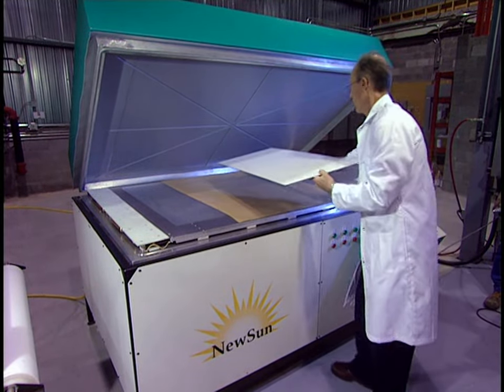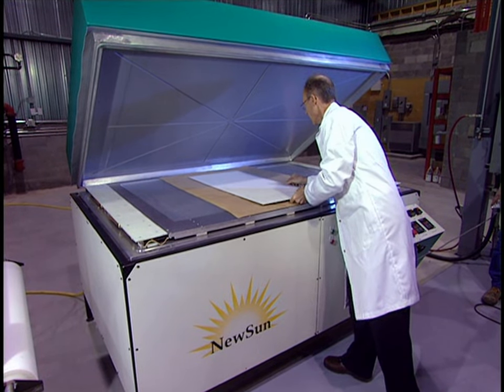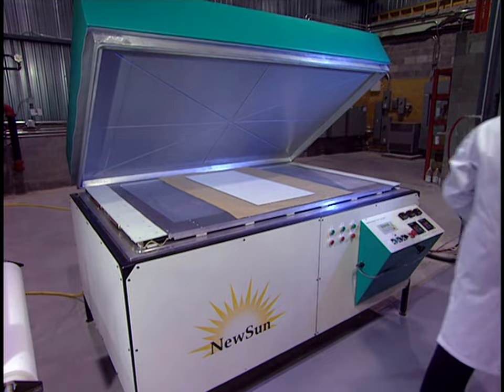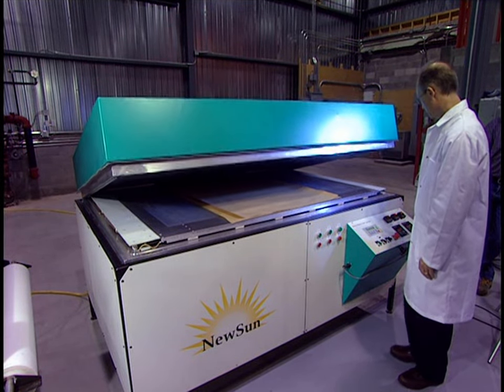To laminate and stiffen the solar panel, it's placed in a heated oven from which air has been vacuumed out. The panel will cook at 176 degrees for 15 minutes. The oven hermetically reseals to proceed with the vacuuming out of air.